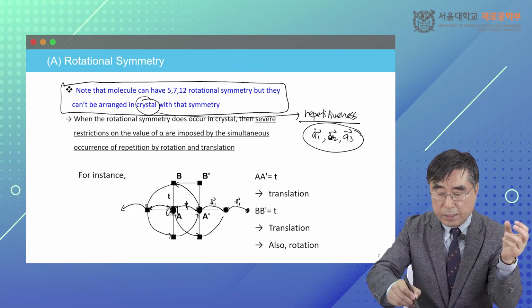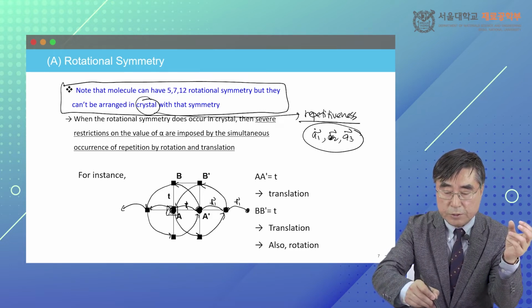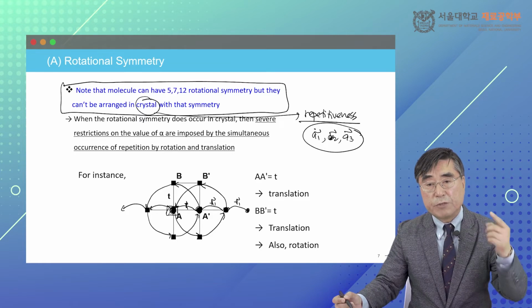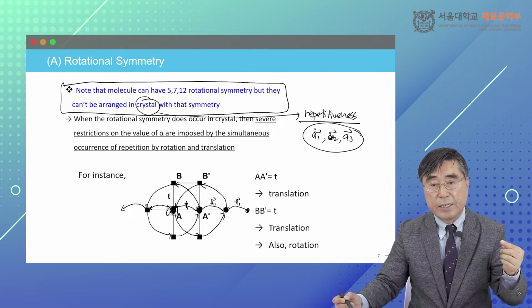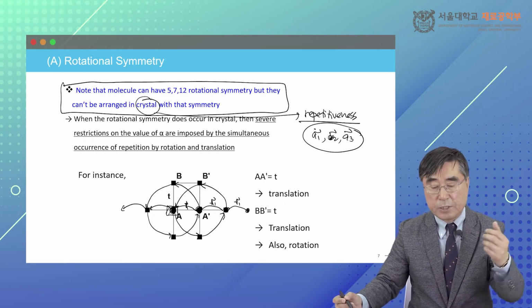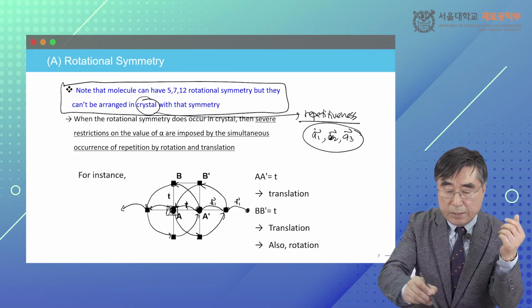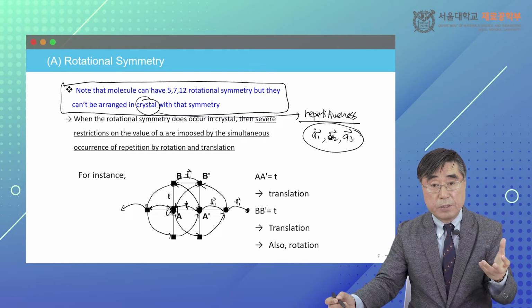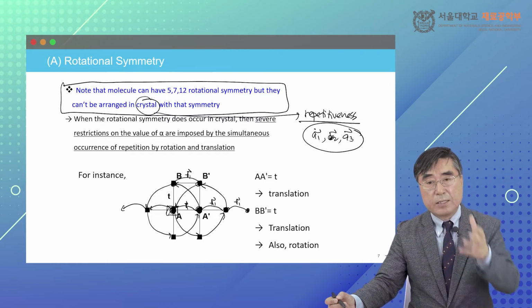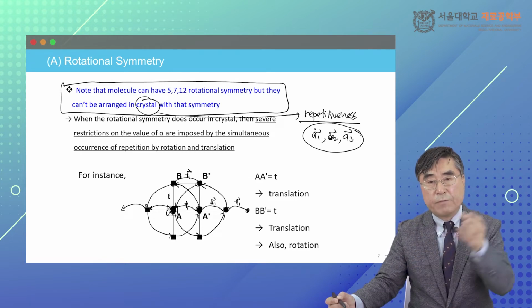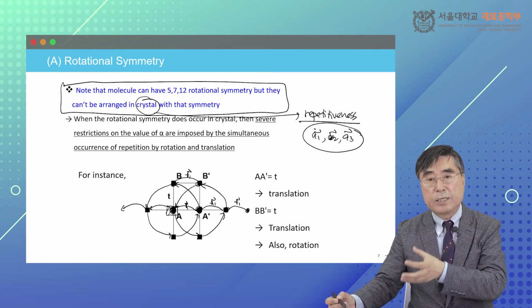So this should be rotated like this, like this, like this, like this. Now the question is, the poles which can be generated by the rotational symmetry, do they satisfy the translation vectors, which governs the definition of crystal structures? In here, this pole and this pole, which is generated by four-fold symmetry, has the separation of T1 vector for the 90 degree rotation. So it matches, it satisfies the basic repetitiveness of these crystal structures. So four-fold symmetry is okay. Four-fold symmetry can be in the crystal structures.